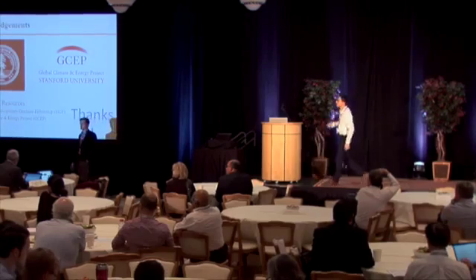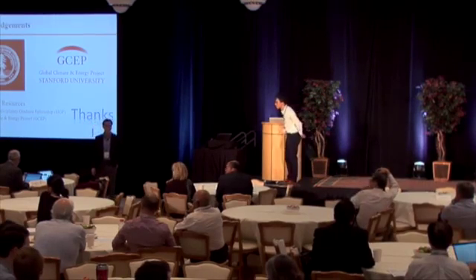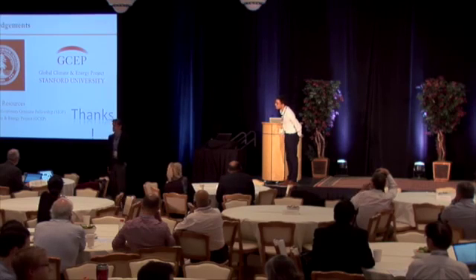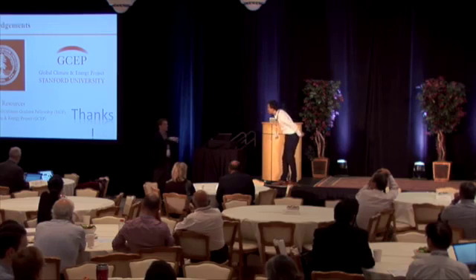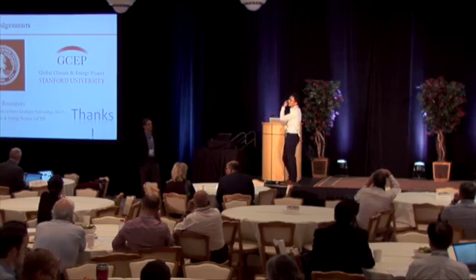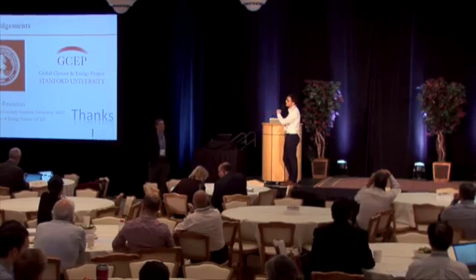Yes. How long have you been able to have it operate? The lifetime of the catalyst. How long have you pushed it, to several days or? So the last one I showed you is the 200 hours without any degradation. That correlates to maybe less than 10 days, but more than 1 week. But the stability of a catalyst, when you test it in the lab, is also limited by the electrode you use. So there is one issue that you need to develop a very robust electrode to hold those catalysts. You mean the current collector? Yes, current collector, yeah.